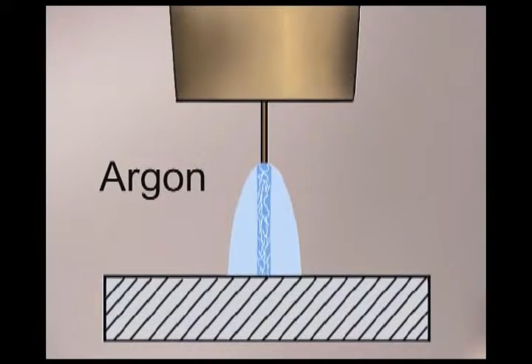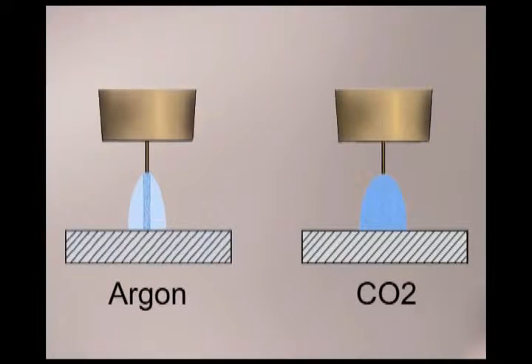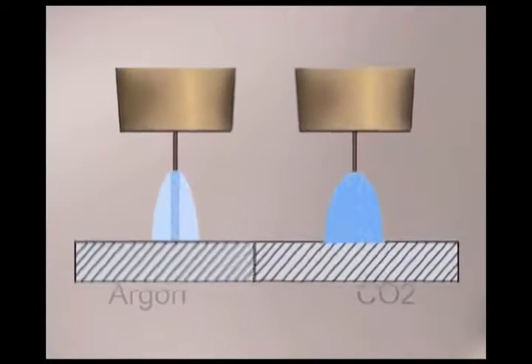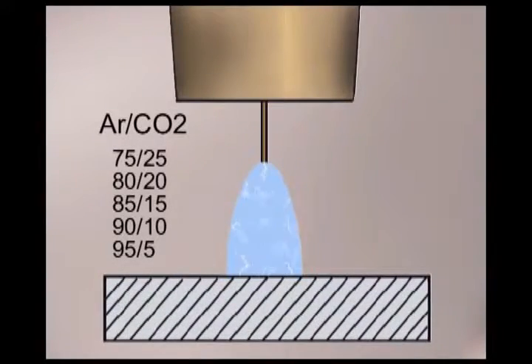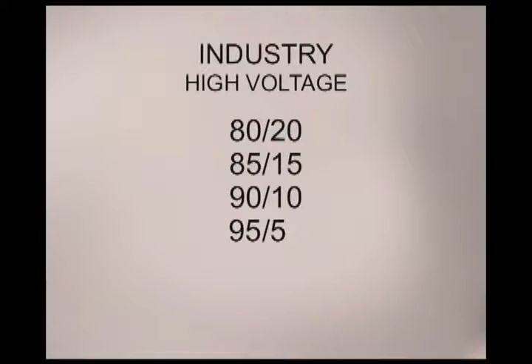Pure argon, on the other hand, transfers current extremely well. Requiring less voltage, argon produces a narrow, dense arc stream with a secondary stream that has very little energy. On carbon steel, welds made with pure argon would penetrate in the center, but the filler metal would not fuse along the sides. What they've done is mix carbon dioxide with argon in varying amounts to provide sufficient arc energy at lower voltages. The gas blend is chosen for the amount of this arc energy it provides, and most of the argon-rich gases are used with high voltage in production welding.